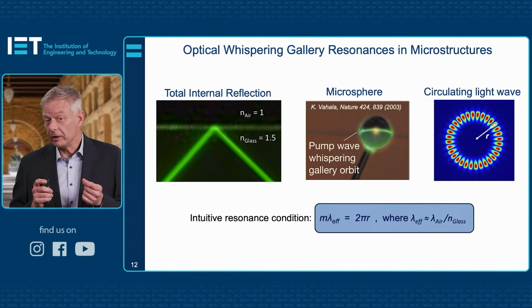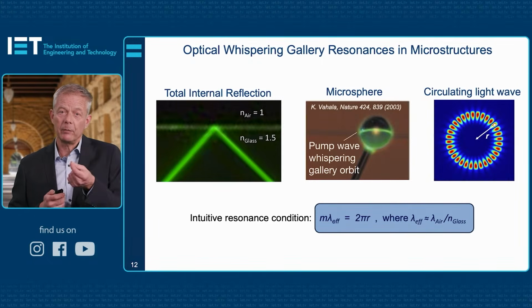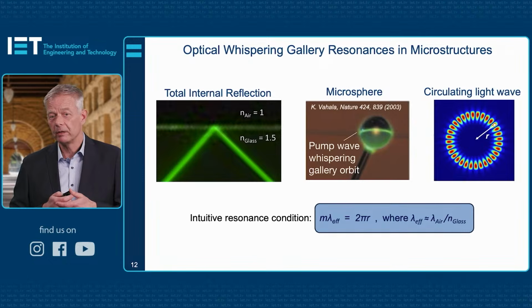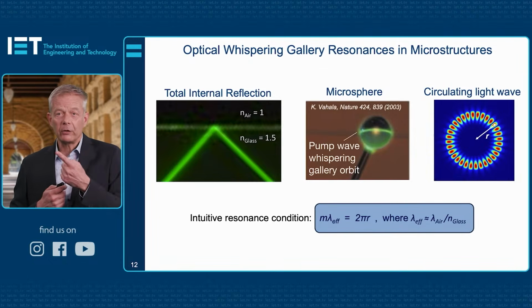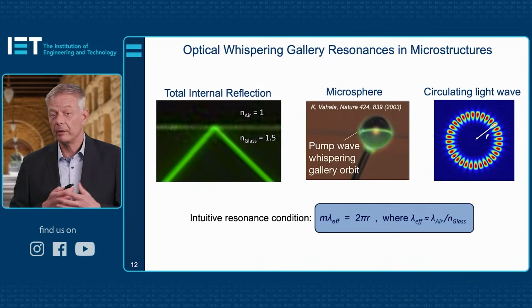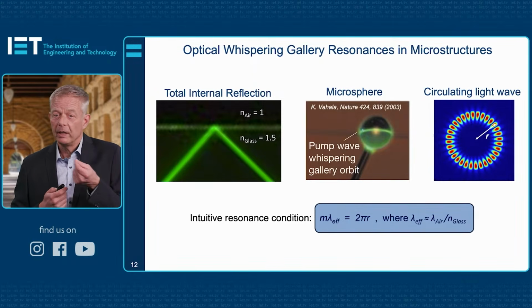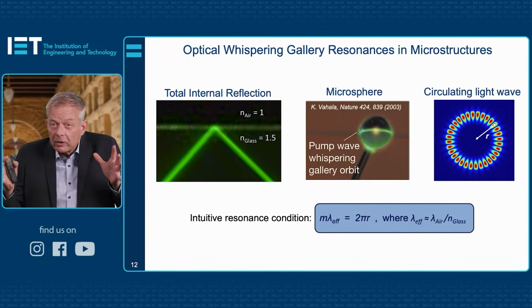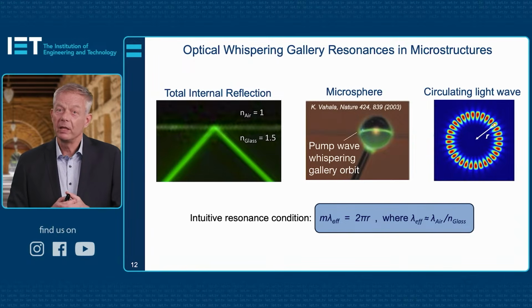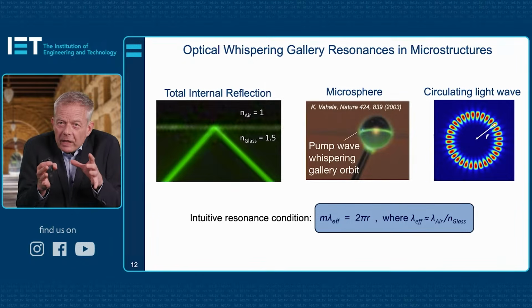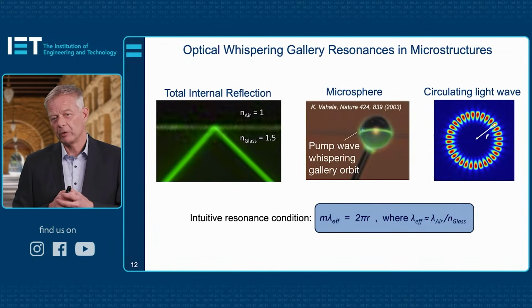Now one can get a resonance. One meets an intuitive resonance condition where an integer number m times the wavelength inside the glass fits fully around the circumference, 2 times pi times the radius. Here the effective wavelength is really the wavelength in air divided by the refractive index, because in this glass medium the wavelength shrinks a little bit, and that's why one can resonate it nicely in a smaller sphere.